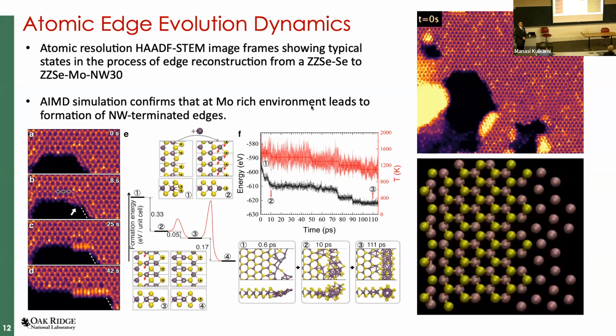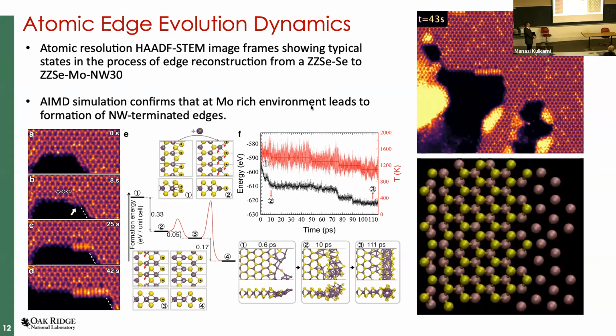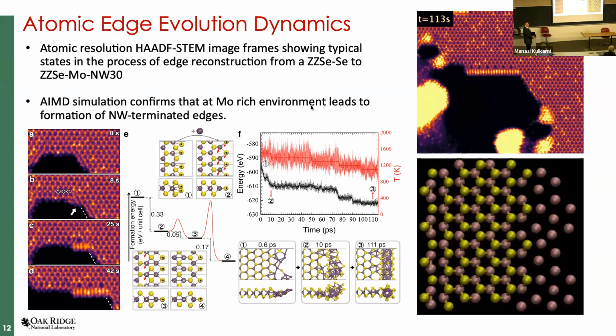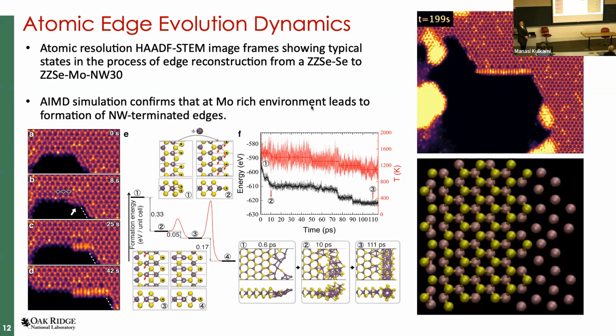So it's one thing to be able to see these dynamics. I'll kind of point to the reaction barriers and pathways in this slide. I'm sorry, it's pretty busy, but I'll try to make a point. If you're doing these experiments, and if you focus on this time series of ADF STEM images, you can kind of see that the structure at the edge is starting to reconfigure, right? Because we're at such high resolution, we can know every single atom where it is and how it's transforming in the process. But even better than that, we can work with folks that have theory expertise that do density functional theory that can basically help us understand the reaction pathways and calculate the energy barriers. So when we're talking about transformation mechanism, we want to understand the reaction barriers, how easy it is for it to move, and also the pathway it takes to do that, right? So this is just a nice example that shows, I won't go into details, but from our images right here, we're able to take density functional calculations and calculate the energy that it takes to form at these different stages during the transformation process.